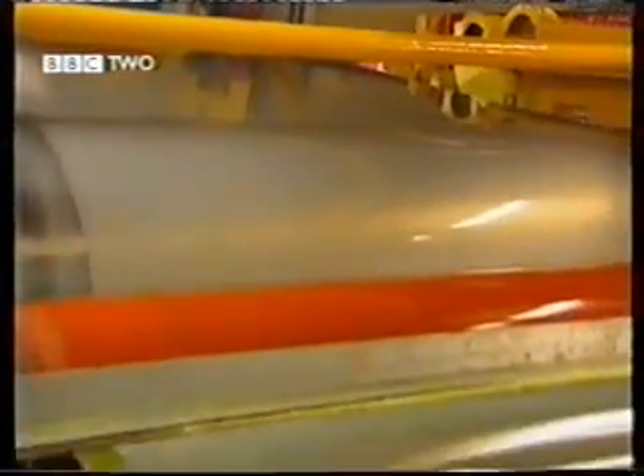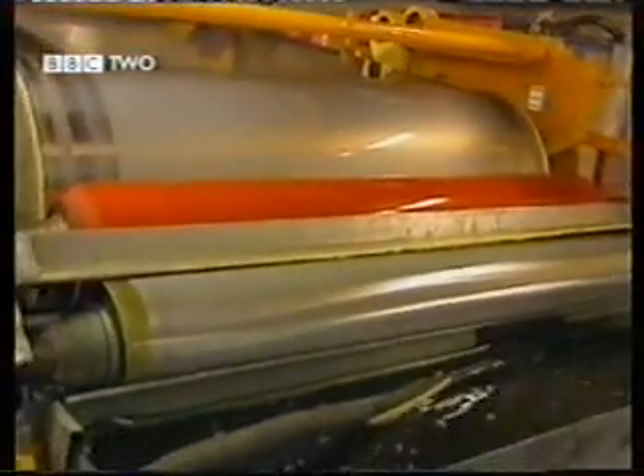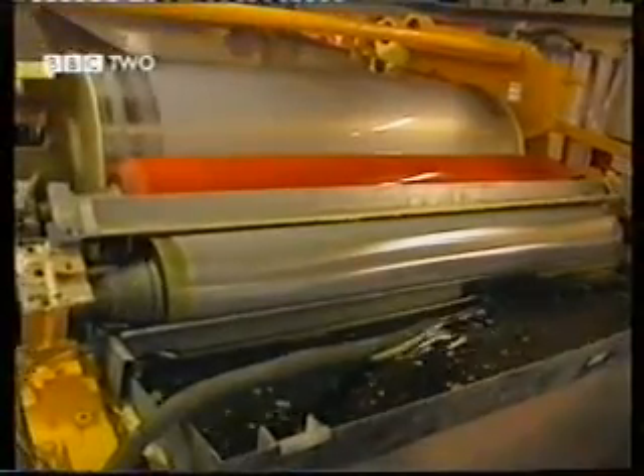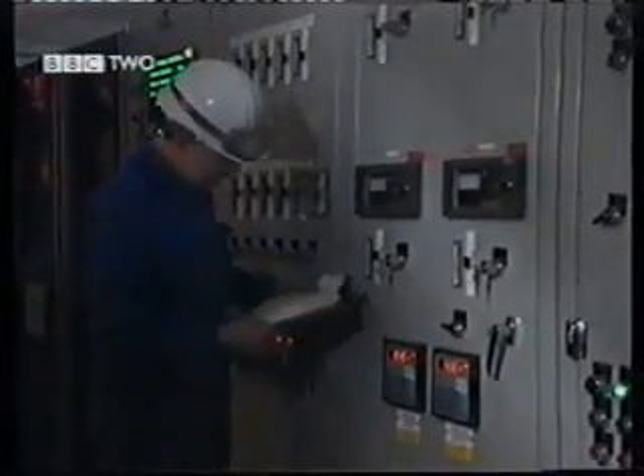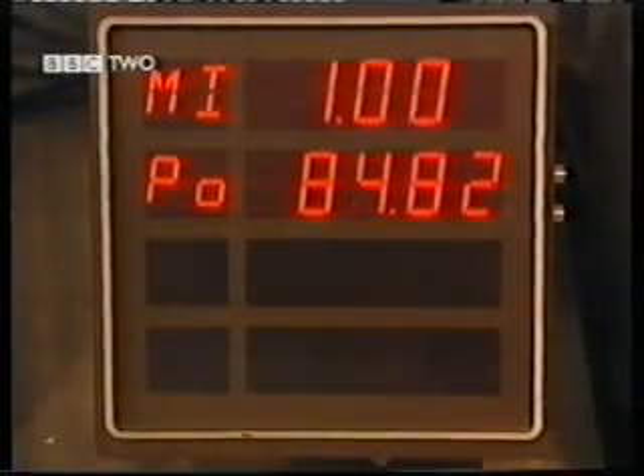Now for a subtle change of emphasis in anti-corrosion strategy. Can we do better than just using zinc? Electroplating a zinc-nickel alloy provides a thinner, harder layer that's better for welding. Increased protection against corrosion can be achieved by coating this layer. First with a very thin deposit of chromate to help bond a lacquer onto the zinc-nickel surface. In the oven, the lacquer is cured to give an organic polymer about 1 micron thick.